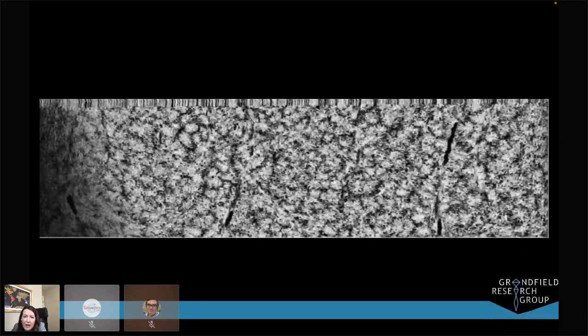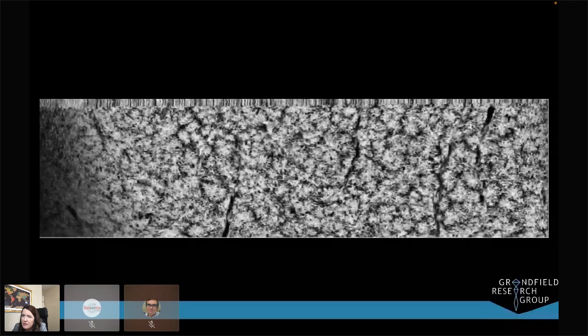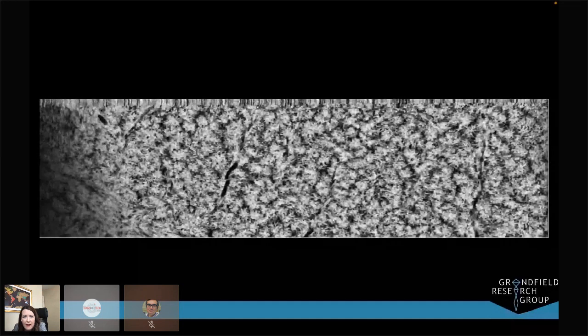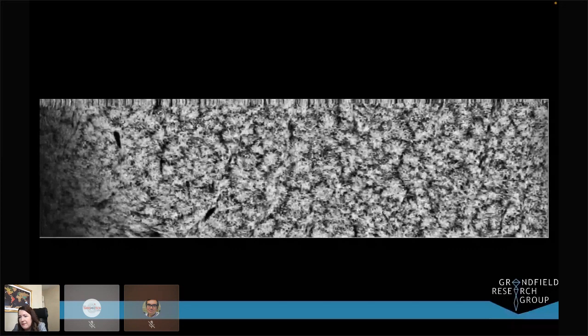What we noticed for the first time was something really interesting. Everywhere else, we see these circular type features across the entire bone structure, these round rosette type features. This is something we hadn't noticed across a huge volume in bone before. We can see that these features are everywhere—the mineral is really clustered into these circular features.